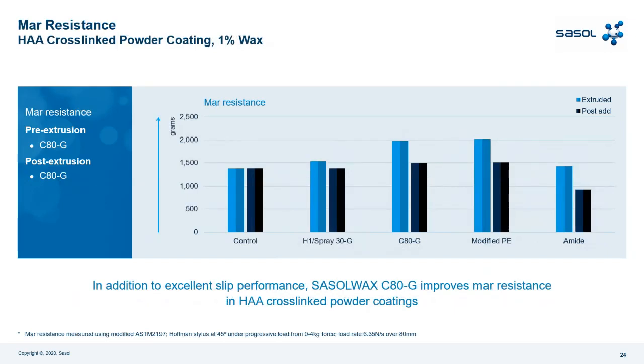Then we have the mar resistance. Mar resistance, again, you can see the control. The control has a low value. We need to check in this case the highest value. The highest value comes in pre-extrusion for Sasol wax C80G. I can tell you Sasol wax C80G is a very good wax. Then in post-extrusion, again, Sasol wax C80G, in this case, we can have a very good result in mar resistance in HAA cross-linked powder coating in pre and also in post extrusion. In post extrusion, you can see that the Modified PE in pre and post extrusion has similar result to C80G, amide a little bit less.